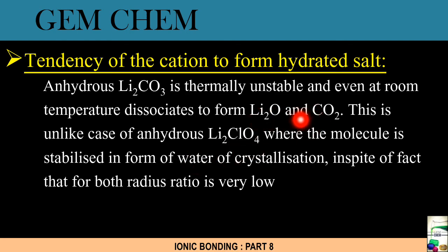Whereas, if we consider LiClO4, in this case, a similar situation, that is the radius of Li+ is much, much lesser than the radius of the chlorate ion, inefficient packing occurs and the lattice will be unstable. But in this case, you have to remember for chlorate, there is a Cl-O bond and the Cl-O bond will not undergo cleavage as there is a greater pi bond character present in it as compared to the carbon-oxygen bond in lithium carbonate. Thus, for gaining stability, Li+ absorbs moisture from air and undergoes solvation, leading to the formation of a large sized lithium-water compound like this. Under this condition, the size of cation and anion becomes comparable and as a result, packing becomes more efficient, thereby stabilizing the compound with water of crystallization.